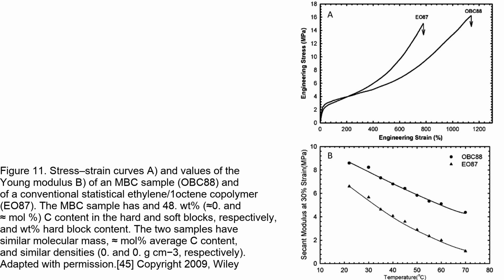The figure illustrates that MBCs have superior mechanical properties, such as higher Young modulus and stress at break, compared to the random copolymer. The results also show that the hard block content in MBCs plays a significant role in determining the mechanical properties. Additionally, the MBC sample exhibits strain hardening and high ductility, even at high temperatures and deformations.